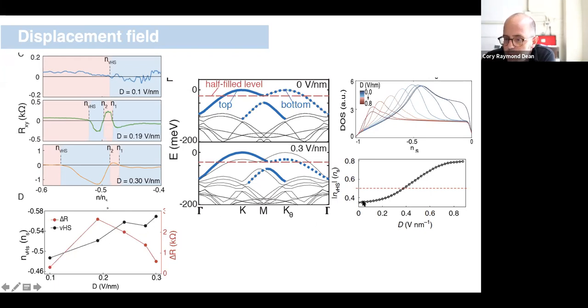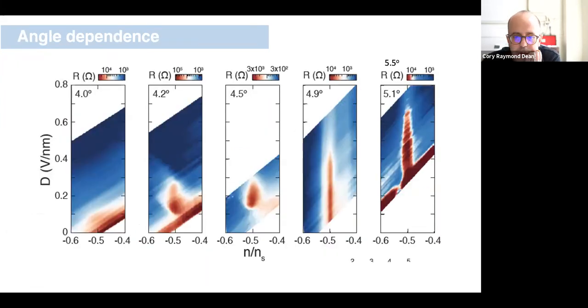And here's the theory prediction from single particle band structure calculation, identifying where in filling the Van Hove should be positioned as a function of displacement field. And the argument here is that we see a fairly nice qualitative, if not exact quantitative, correspondence. The qualitative argument is that at zero displacement field, the Van Hove begins slightly below half filling. And as we increase this displacement field, we can push the Van Hove to fairly far above half filling. And that's exactly what we see in our data. Okay, so fairly good agreement, we think.